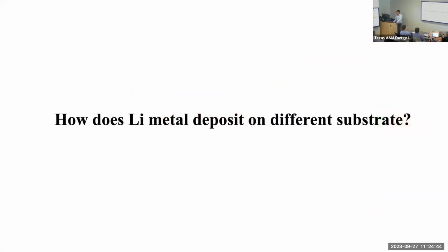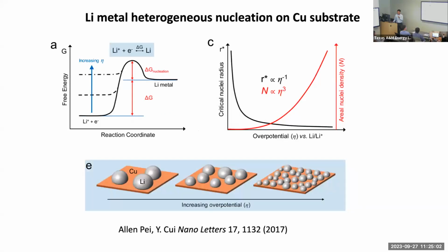Now let me share with you some of our findings. The first question we ask is, when you deposit lithium and strip lithium, how does the deposition happen? Particularly right at the beginning. How does that happen? It was not understood at all. So in 2017, we looked at this problem deeper. You take lithium ion and electron, depositing, forming metallic lithium. You have to cross the energy barrier right there, particularly this nucleation event, to deposit on different substrates.